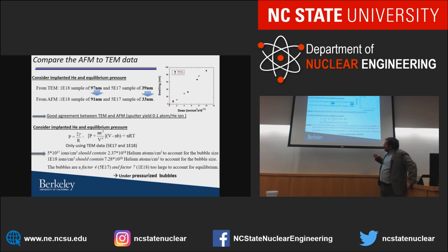One question is, what is the pressure in these bubbles? That's a relevant question because that tells you how much helium can be accommodated in them, and is there any strain associated with them. So when you assume van der Waals gas laws and typical pressure and surface tension equations, you can calculate that when you implanted 5 times 10 to the 17 ions per square centimeter, the bubbles are large enough and many enough that you can accommodate 2.3 times 10 to the 18 heliums per square centimeter. So your bubbles are much larger than they need to be.